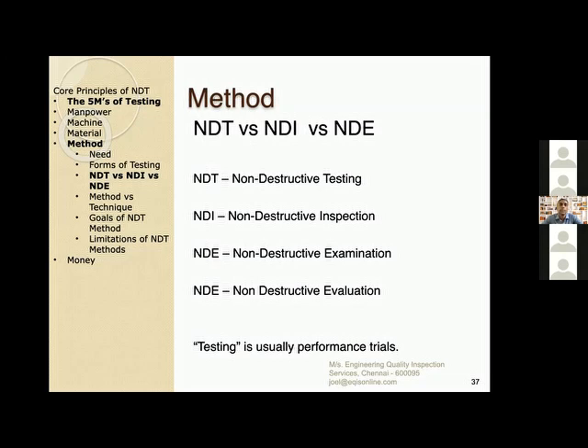So testing is just one data point. Inspection is a collection of data. And examination is like wisdom from the inspection data. So I make sure I take the inputs from each NDT test, I analyze the pattern, and then I come to an examination point where I scientifically conclude that this is the defect that is available on the equipment. And then we have an evaluation, which is an even more scientific approach, where we bring in all the statistical data over a period of time. We bring in the probability of detection. We bring in a lot of factors, to make sure that it's a very scientific approach to the NDE examination.